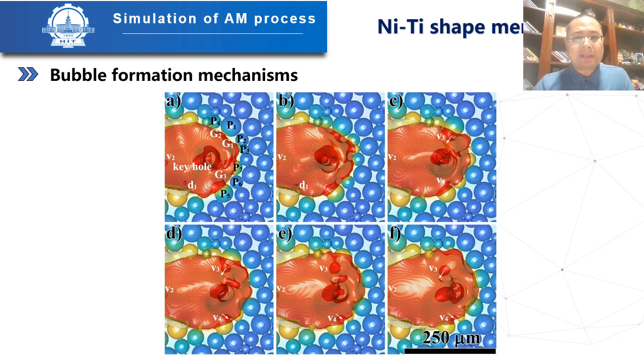So, at the initial stage, there are powders surrounding the advancing melt pool. As the melt pool moves along, these powders gradually melt, and due to surface tension, gaps and gas existing between these powders get pushed out into the chamber. However, in some cases, the gas trapped within these gaps might find itself ensnared within the melt itself, leading to the formation of a bubble V3.